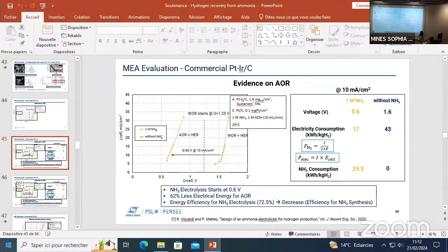You tested your catalyst for maybe 3 hours maximum, I think. More like 1 hour. Yeah. So longer tests are of course required to validate the robustness, but already at 1 hour the catalysts are not durable, so that's why we stopped.